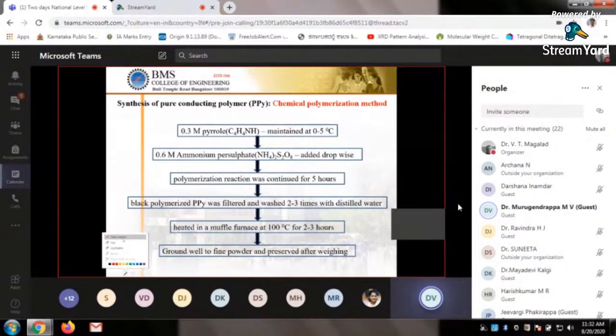So what we are doing is taking a monomer and an oxidizing agent, and then a polymerization reaction takes place, and we get a black polymerized powder. Actually, it is a precipitate, and then we have to filter and wash it, and then keep it in a muffle furnace at 100 degrees centigrade for 2 to 3 hours, and we'll get a fine powder. So that is how we synthesize polypyrrole by a simple step.